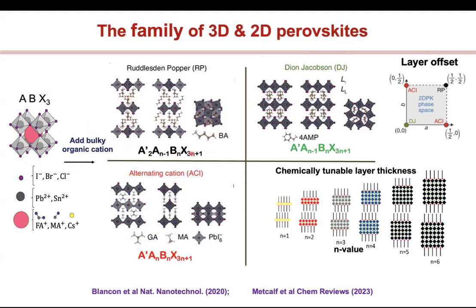It has this formula. You see that this part remains the same, but now I have this A2 prime, which is this bulky cation, in this case butyl ammonium, basically a 4 carbon chain. That forms this layered structure, and it sits as a spacer cation between these octahedral layers of the perovskites. Okay. And you can have small changes in it, and it can form what is known as a Ruddlesden-Popper phase, or a Dion-Jacobson phase, or an alternating cation phase. These are just small structural differences, just the way the unit cell is offset from each other. But the nice thing about this is that you can now chemically tune these layers, right?